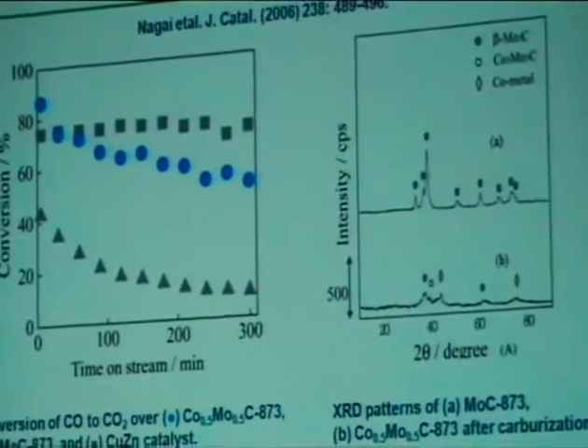And one advantage of this molybdenum carbide is also sulfur tolerance. So we look for the active phase of this molybdenum carbide and the cobalt molybdenum carbide. And Nagai proposed that the cobalt molybdenum carbide is stable towards the water gas shift reaction. So the increase in activity, they're proposing, is likely due to the increase in the carbon deficient sites and the cobalt atoms of the cobalt molybdenum carbide.